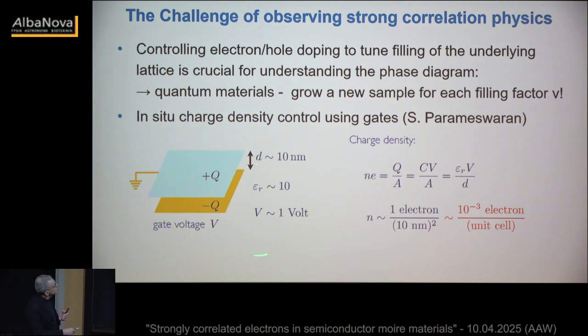So one possibility, and this is a discussion from Sid Parameswaran, which I like very much. We can say, well, instead of doping, can we not just use an electrical gate? After all, we can think about the capacitive structure, and if we apply a voltage, let's say between two plates, let's assume that their separation is 10 nanometers, but this could be 100, doesn't matter. Then I can apply a voltage of about 1 volt before the material in between starts to leak and doesn't really work as a nice capacitor. Okay, so if I increase the distance to 100 nanometers, I can apply 10 volts. But what is really limiting here is the electric field that you can apply, which is about 0.1 volts per nanometer. Okay, so there are some devices that go up to volts per nanometer, but this is kind of the range.